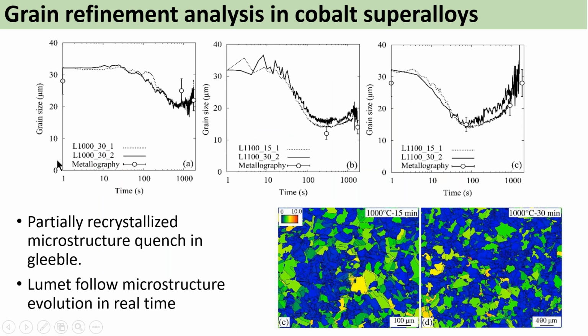So here is the result where we have the grain size in the vertical axis, time in the horizontal axis. You see here the grain size is always the same, not very much affected by the temperature during the strain. And as the time is passing during the isothermal holding, we have a grain refining occurring during the isothermal holding. And this grain refinement occur at different time depending on the temperature at which the deformation was applied. So you see that in the three conditions, we were able to capture the grain refinement occurring during the deformation.